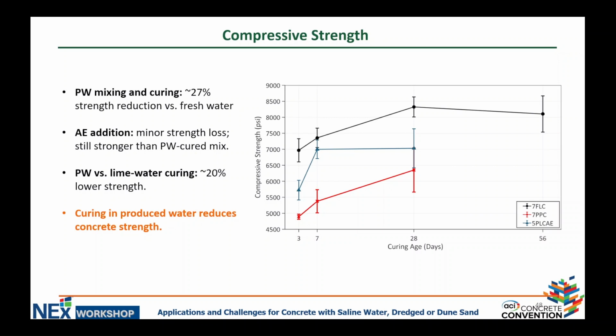That means curing itself is playing a very important role here. Making concrete with produced water and curing it in lime water only decreased the compressive strength by 8%. But when we cured it in produced water, the decrease was 27%. Actually, we decided to do the curing in lime produced water to decrease or to limit leaching. But it seems that the opposite happened. Something is wrong, okay? So that is the main thing we can see here, that curing regime plays a very important role.